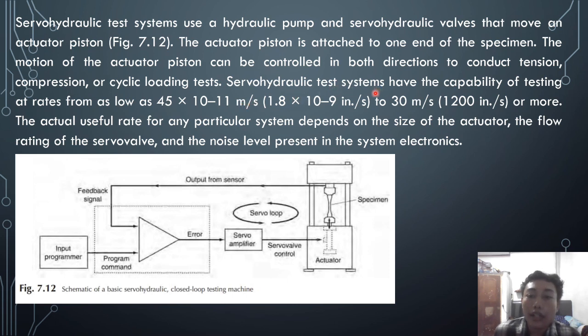Several hydraulic systems have the capability of testing from as low as 45 x 10^-11 meters per second, or 1.8 x 10^-9 inches per second, to 30 millimeters per second, or 1200 inches per second or more. The actual useful rate for any particular system depends on the size of the actuator, the flow rating, the servo valve, and the noise level of the system electronics.